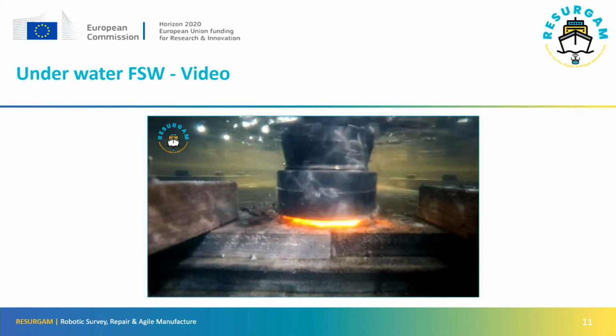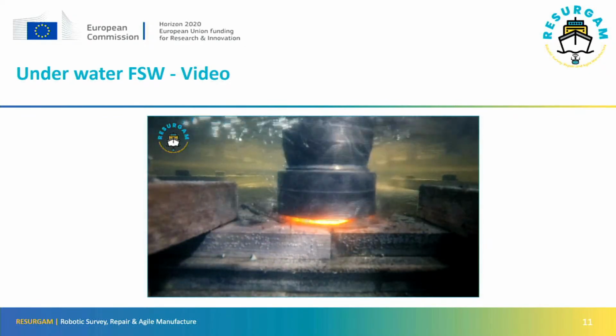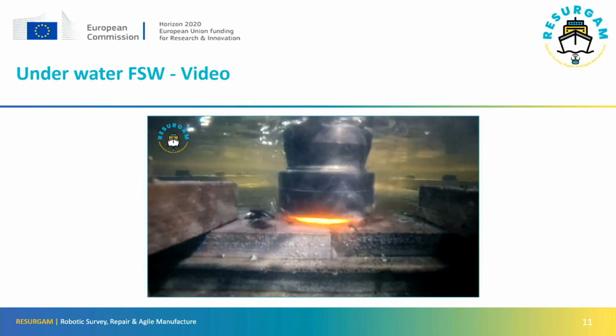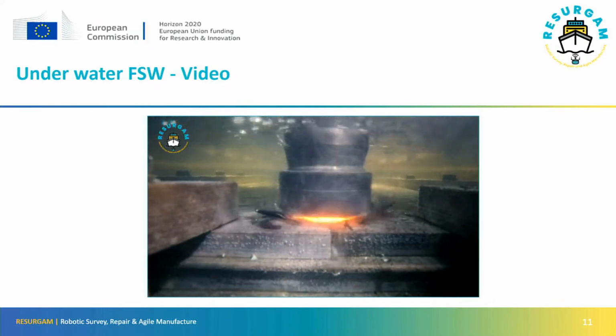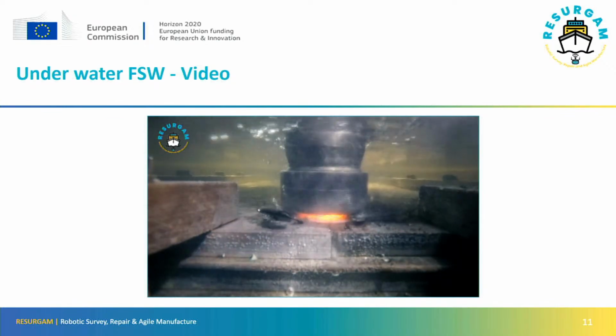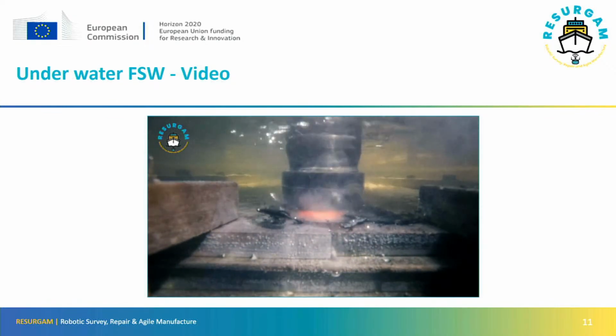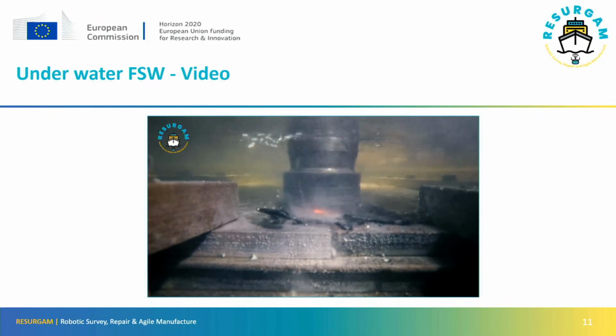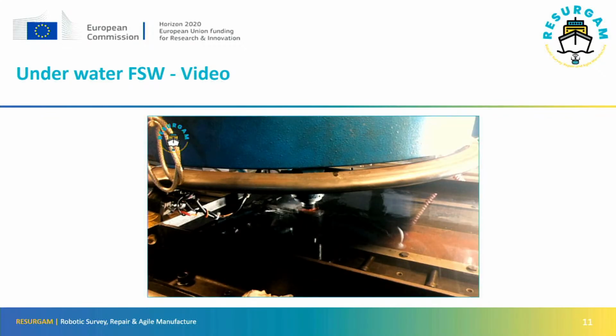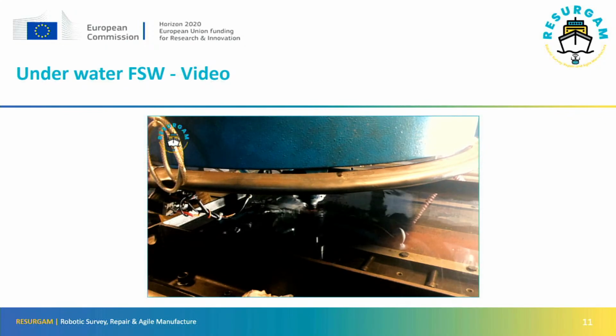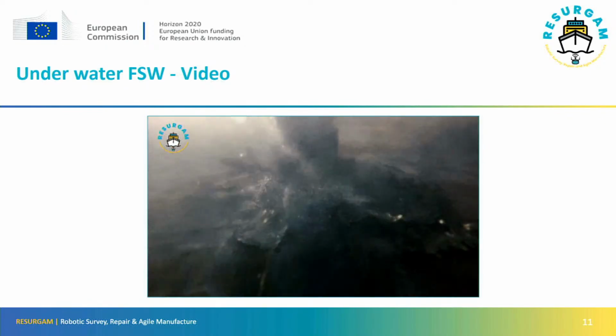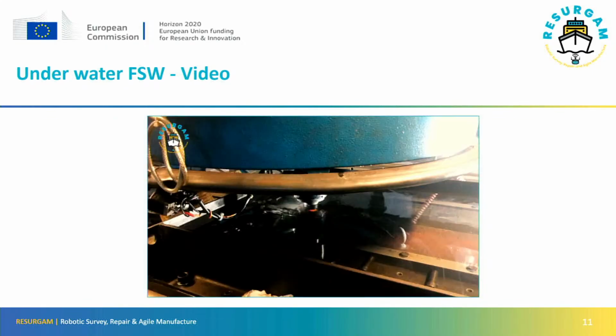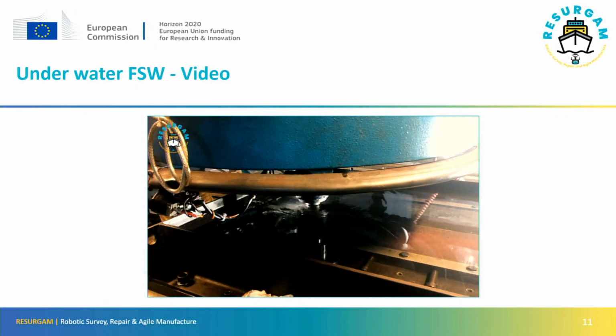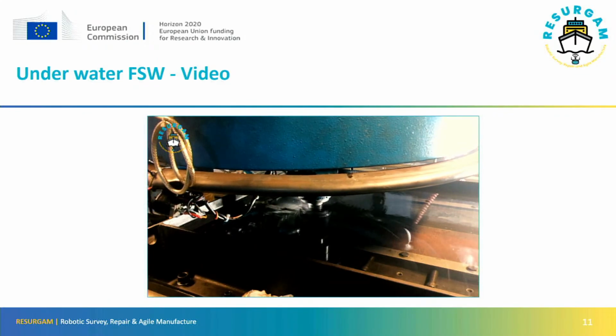As the friction stir welding tool rotates, it begins to generate heat, softening the steel immediately beneath it and embedding itself into the steel. Bubbles of steam can be seen originating from the contact area between the tool and the steel being welded. Once sufficient heat has been generated to soften the steel, the tool begins to traverse along the joint line, stirring the metal and joining the two plates together. Once the weld is complete, the fabricated test coupon is removed from the water tank.